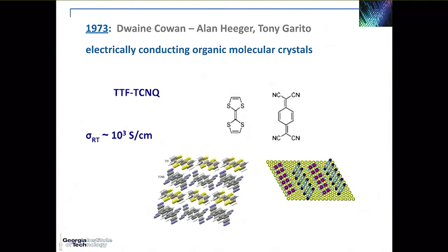A first important discovery was made independently in the lab of Dwaine Cowan at Johns Hopkins and in the labs of Alan Heeger and the late Tony Garito at Penn, who discovered electrically conducting organic molecular crystals with conductivities at room temperature on the order of 1,000 Siemens per centimeter. That's basically the same kind of electrical conductivity as the one you get in the polycrystalline copper wires that we use.